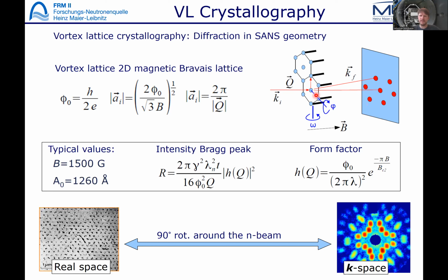And as the lattice spacing of the vortex lattice is just given by the magnetic field, we get a very simple relation of field, scattering angle and the reciprocal lattice vector. I've given you here some typical values. For a pretty low field of 150 millitesla, we get a lattice spacing of roughly 1200 angstroms, which leads to a very small Bragg angle of roughly 2/10 of a degree, I think. The intensity of such a Bragg peak, and this is really a Bragg peak, not a diffuse small angle scattering, is mostly given by the form factor, and this is in turn given by the shape of a vortex.